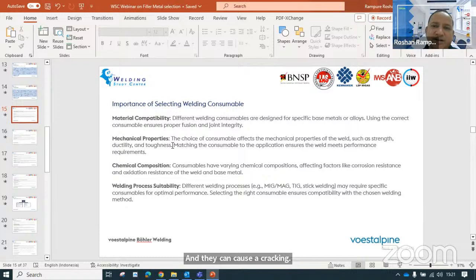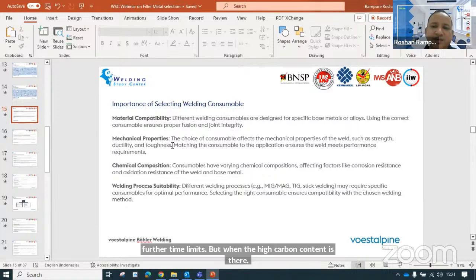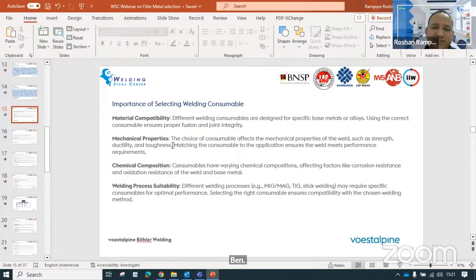But when the high carbon content is there, then during welding, due to the presence of very high carbon content, hard phases will be formed, like Bainite phase or martensitic phases may be formed due to rapid cooling of the base material. Such difference between the microstructural phases from the unaffected base material to the HAZ and the weld metal will lead to generation of hard phases, and that could lead to cracks generated due to welding.